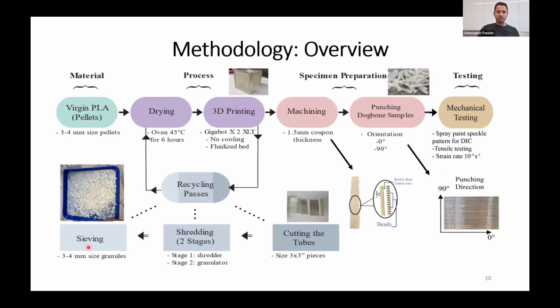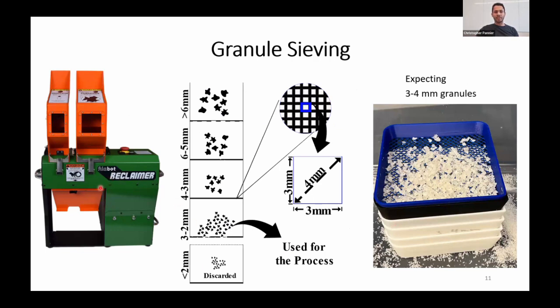So since we're speaking about sieving, for the sieving process, we have used a filament reclaimer, which uses 2 processes of sieving, and several sieves that we printed in-house, which have different dimensions, as I was showing here. So the largest sizes are on the top, and then these sieves will be placed from the top, and then we would shake them side to side or up and down manually until we get to the desired sizes that we would like to use for our process. Anything lower than 2 mm, we would just discard or keep aside for other recycling purposes as well.